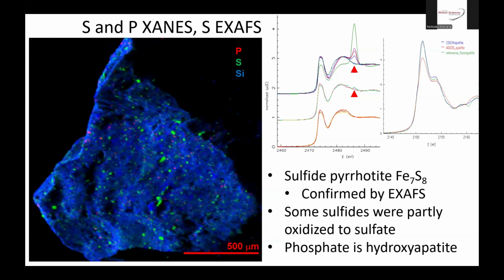So in this case, does self-absorption matter, for example? Is that affecting your analysis? There is some self-absorption for sulfides, for metal sulfides. Typically, the metal absorbs so heavily that it reduces the amount of self-absorption. But you never eliminate it completely, and it's always a concern. And I will get to that in a bit. I have a whole slide on self-absorption because that becomes important for a lot of details.